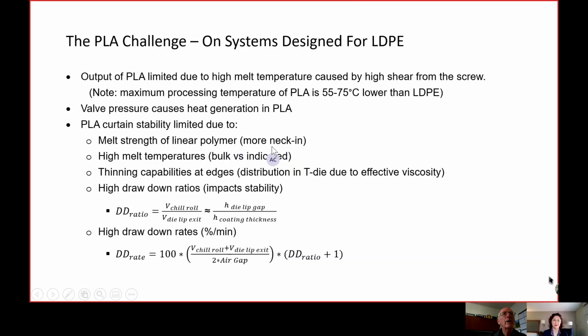Other challenges we have with PLA is because of this linear polymer, it tends to neck in more than the low-density polyethylene, which causes us to get useful sheet to try and lower the die into the nip, shortening that air gap, which now increases the rate of extension of the polymer in the air gap, further destabilizing the melt curtain.